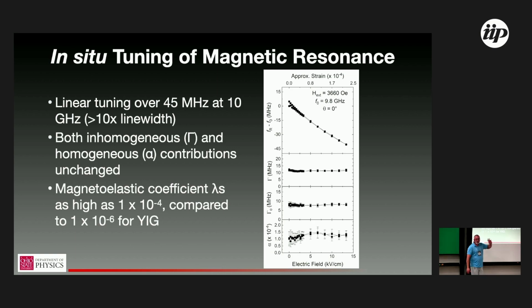So it's tunable and gentle, or reproducible, however you want to think about that. Well, it's not actually squishy. It's just we're not cracking it by stretching it, because that's one way in which you can induce changes: introduce microfissures and defects, and not even macroscopic cracks, but threading dislocations or something that would propagate. We don't see any evidence that that's what's happening.